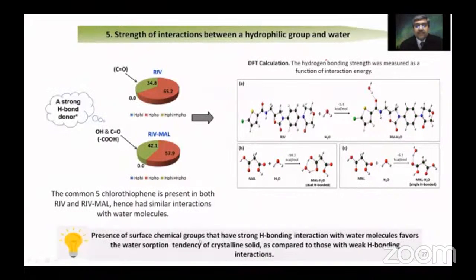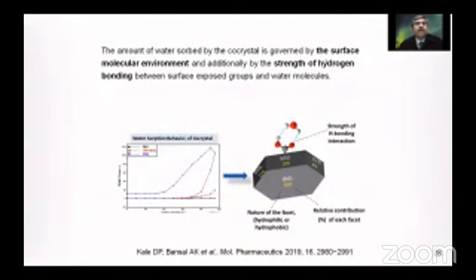So the presence of surface chemical groups that have strong hydrogen bonding interaction with water molecules favors the water sorption tendency of a crystalline solid as compared to those with weak hydrogen bonding interactions. So what came up from this study was that the amount of water sorbed by the co-crystal is governed by the surface molecular environment and additionally by the strength of the hydrogen bonding between the surface groups that are exposed and the water molecules. So this is the entire study in a nutshell, that we first evaluated the nature of the facet in terms of hydrophilicity or hydrophobicity. What is the relative contribution of these to each facet, and what is the strength of the hydrogen bonding interaction between the groups that were exposed on the facets and the water.